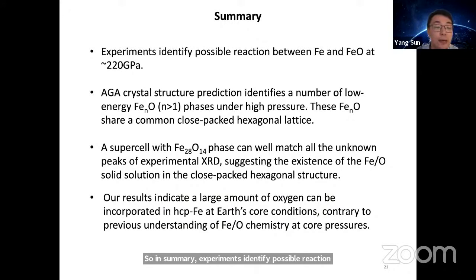We use this adaptive genetic algorithm crystal structure prediction to identify a number of low energy iron-rich phases at high pressure. So this iron-rich oxide all share a common close-packed hexagonal lattice. A supercell with Fe28O14 phase can well match all the unknown peaks of experimental XRD, suggesting the existence of iron-oxygen solid solution in this close-packed hexagonal structure.